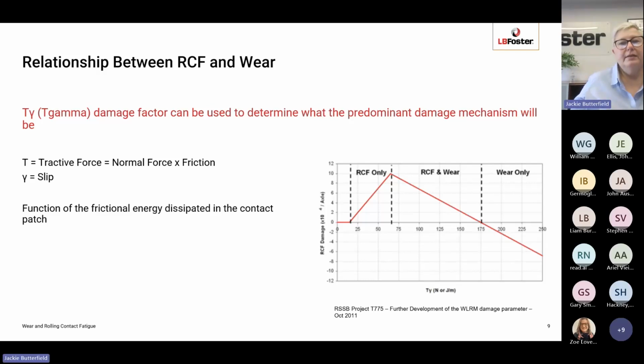You have T gamma along the x-axis, and then you have areas on the graph where you have rolling contact fatigue damage only, a mixture of rolling contact fatigue and wear, and also wear. So by controlling those T gamma values, you can balance between rolling contact fatigue formation and wear. Some railroads call it the magic wear rate. What you're trying to do is balance the wear rate with removing those shallow rolling contact fatigue cracks so that they never get to a stage where they will turn down through the rail and cause catastrophic failure.